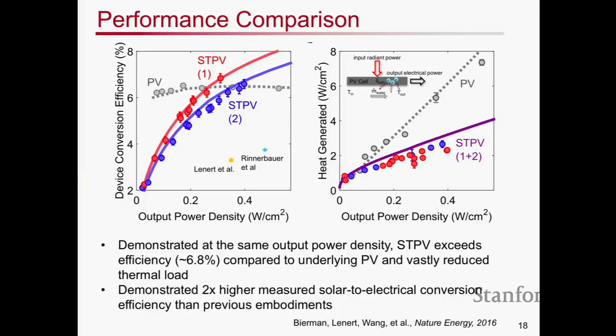So this is now looking at the device conversion efficiency as a function of the output power. And as expected, the photovoltaic conversion process is relatively constant. And with our improved design, you can see here for different area ratios, I believe this one's about 8 and this one's 12 here, that at this point there is a crossover such that, in fact, you can exceed the device conversion efficiency compared to that of a PV cell. Just for reference here, this is some of the earlier reported works from our group and collaborators.